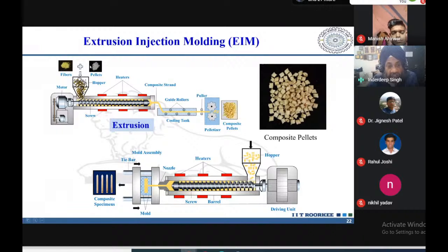So we have fibers and pellets here, which we combine together in the hopper, and from the hopper we extrude this material using the various heaters. The pellets melt and the fibers are encapsulated or impregnated with the polymer, and then this combination of fiber and polymer comes out as a composite strand or extrudate, which is cooled down and finally pelletized. Pelletized means we cut it into a standard size, or composite pellet.